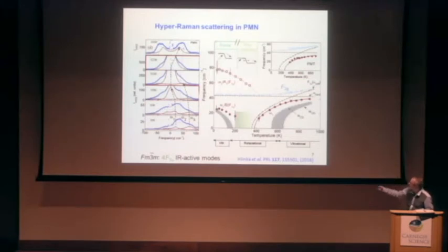So it looks like there is a soft mode like this, and this second mode here was explained as originally an infrared inactive mode, F2g symmetry, which is seen in Raman scattering, and due to coupling of these two modes, it becomes infrared active finally. And there is another component of the soft mode here, hardening, the same as in our previous infrared spectra. So note, this is originally a non-active infrared mode, but it becomes active through coupling.